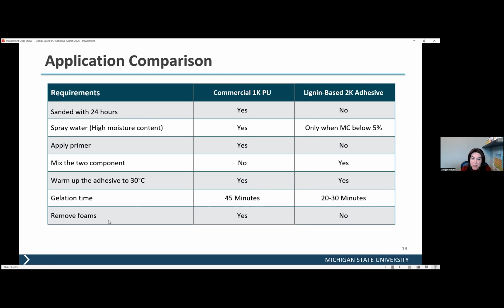With the commercial adhesives, as I mentioned, when the adhesives react with the moisture in the wood, it ends up having some foaming on the side of the CLT samples that needs to be removed. We didn't observe this foaming with the lignin-based polyurethane adhesives.